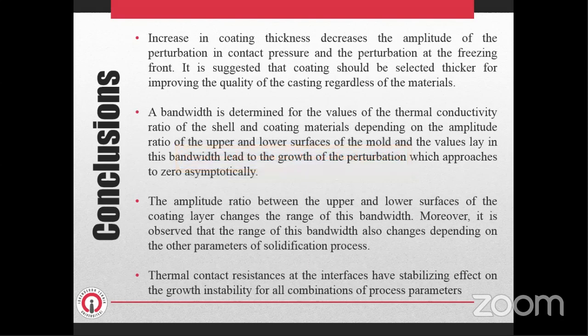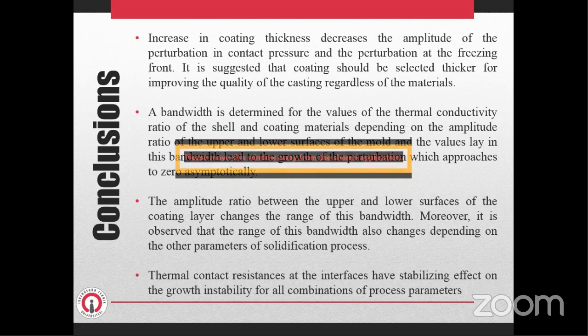Now, I want to summarize my conclusions of this study. Increase in coating thickness decreases the amplitude of the perturbation in contact pressure and the perturbation at the freezing front. It is suggested that the coating should be selected thicker for improving the quality of casting regardless of the materials.